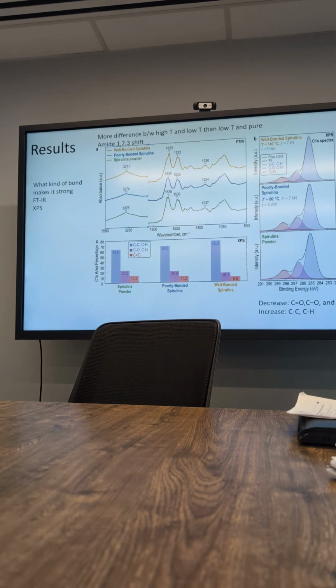So, and then from the XPS we also know there is a decrease in these 3 bonds, but there is an increase in carbon-carbon and carbon-hydrogen bonds. That is because their cell matrix is made of protein and carbohydrate, and most of the matrix is protein, and some of it is carbohydrate. But that's why the shift to more beta sheet is important, and because the bonds that decreased are mostly in the protein and carbohydrate, that matches their assumption.